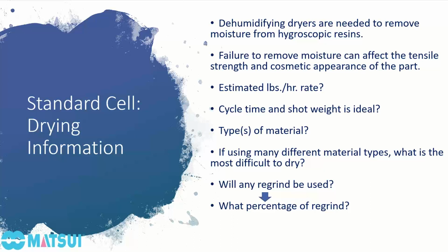These materials retain moisture, and dehumidifying dryers are needed to remove moisture from the plastic. Failure to remove the moisture can affect your parts. It can affect the tensile strength as well as the cosmetic appearance of your parts. So dehumidifying dryers are needed to remove moisture from hygroscopic resins.